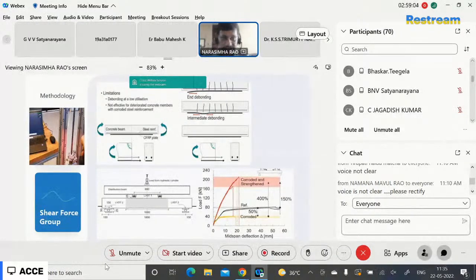Therefore, we have to find out exactly the residual area, the net area of steel available in the degraded RCC column, and based upon that we have to find out the limit of resistance, that is nothing but the stress in the steel multiplied by the corresponding area of the steel, into the lever arm, that is the limit of resistance of the beam. That is coupled with the tension offered by the FRP system, that is the number of layers into the layer thickness into the width of the FRP, multiplied by the lever arm with respect to the CG of the concrete in the compression zone. This combined system will give the moment of resistance.